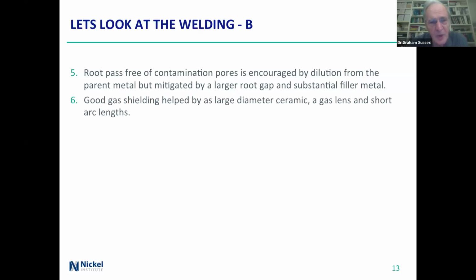Very good gas shielding helps, but you probably need a reasonably large diameter ceramic, maybe even a gas lens. And certainly you're looking at reasonably short arc lengths, because long arc lengths just encourage air intake, and that's bad news for making sure you don't get contamination.